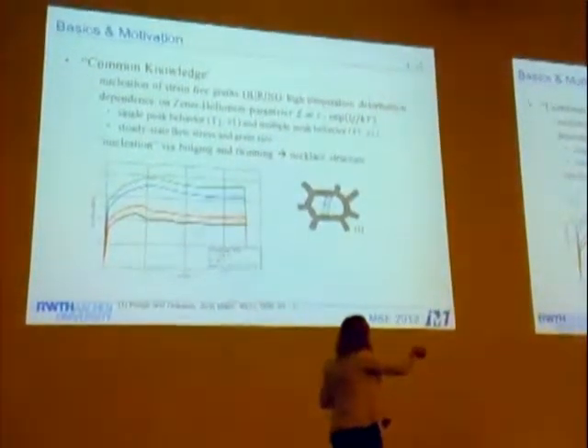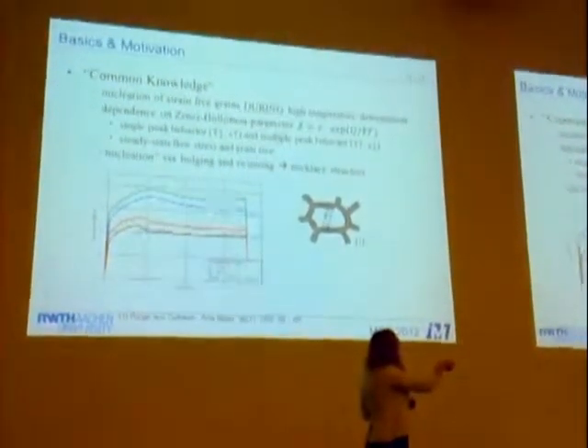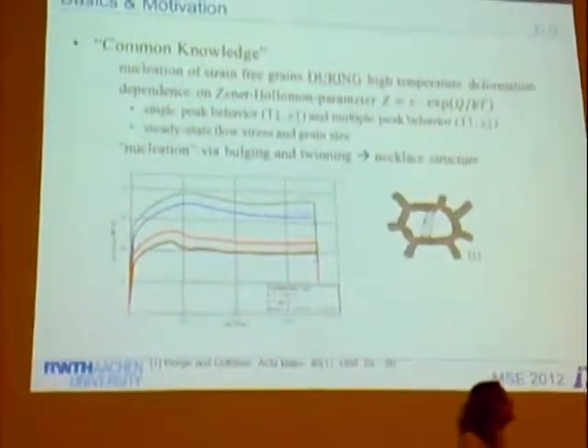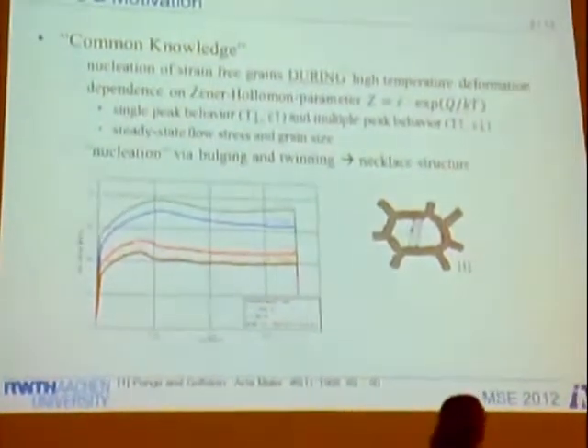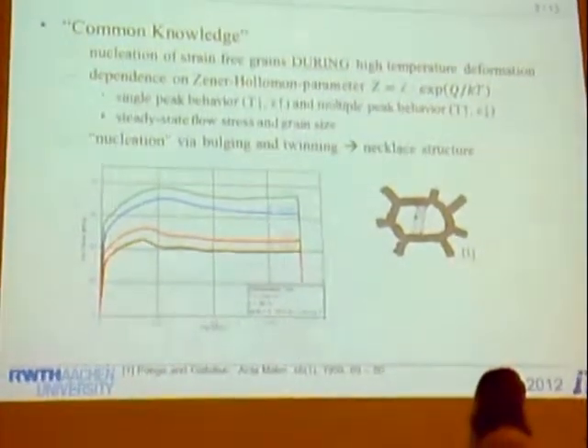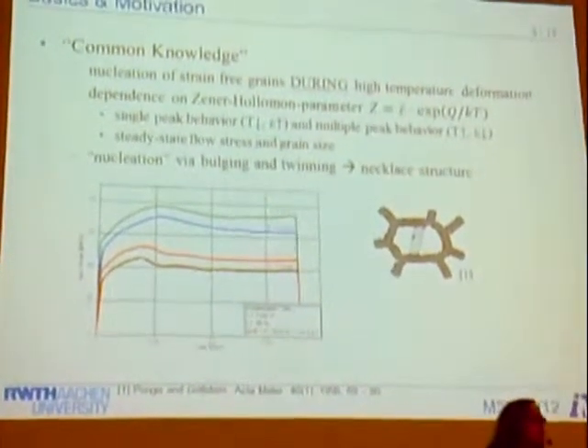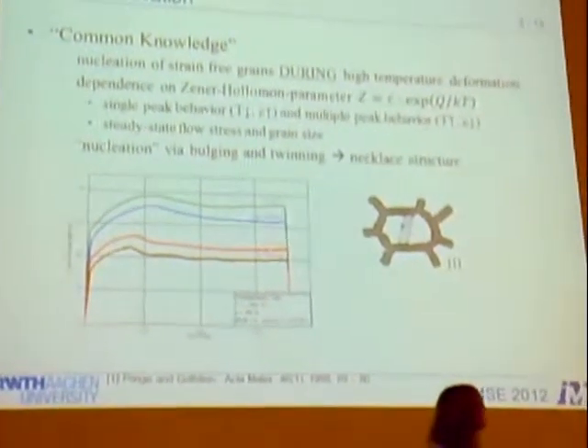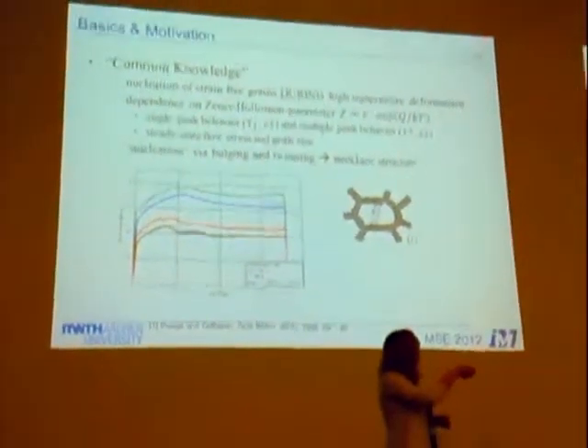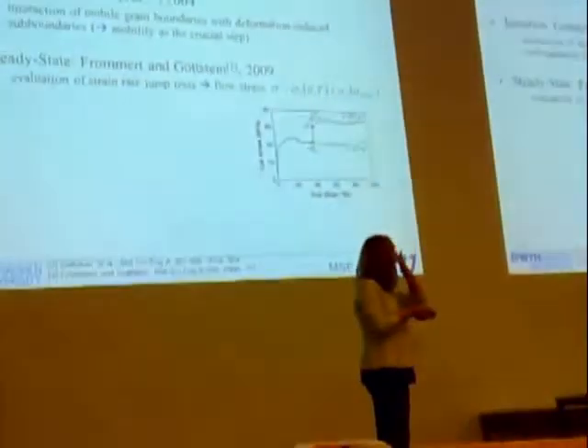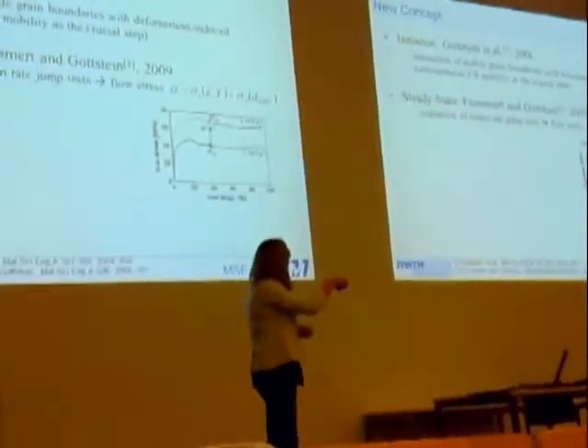dependence on the Zener-Hollomon parameter. This dependence can be seen in flow curves when you have a change from a single peak behavior to a multiple peak behavior. But much more important is that we have this very nice steady-state flow stress and also a steady-state grain size, which can be adjusted by the change of the strain rate. It has been evaluated, and it has been shown there that you can decompose the flow stress in this change into two parts.